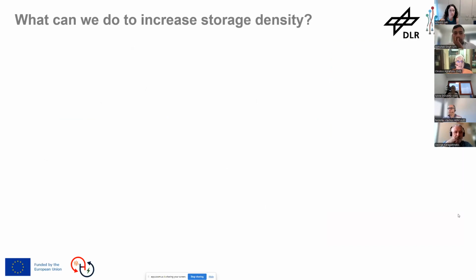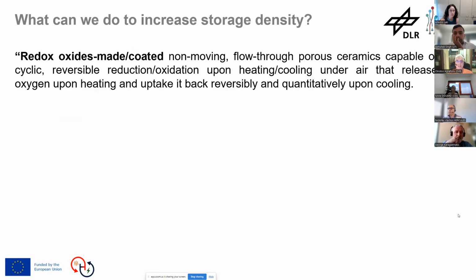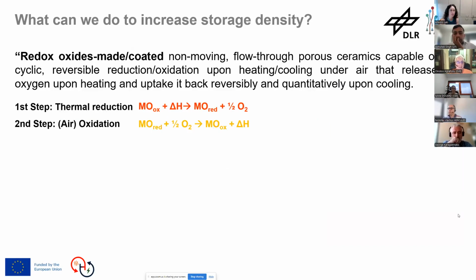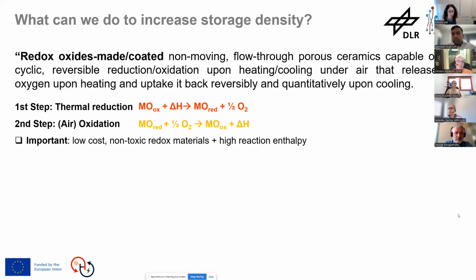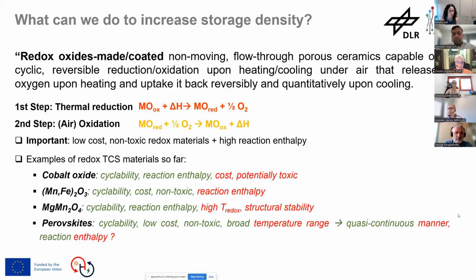Okay, and how can we increase the storage density? As I said before, we have to make this kind of oxides and exploit this kind of reactions as they are shown here, in a very generic scheme. Upon heating, the oxide loses some of its oxygen and transforms to the reduced state, and then when we need extra heat, we can pass, for instance, air through the porous body, and then recover the enthalpy of the exothermic oxidation reaction. The idea is, of course, we would like to have low-cost, non-toxic redox materials and high reaction enthalpy, but of course we cannot have all of this.